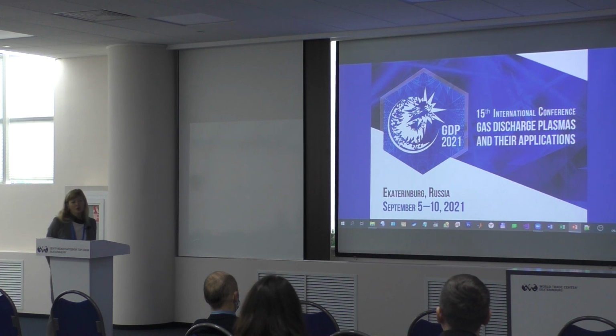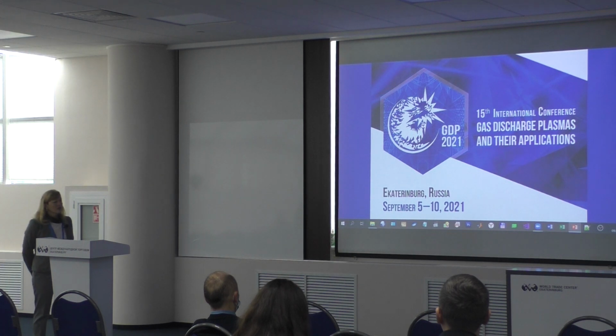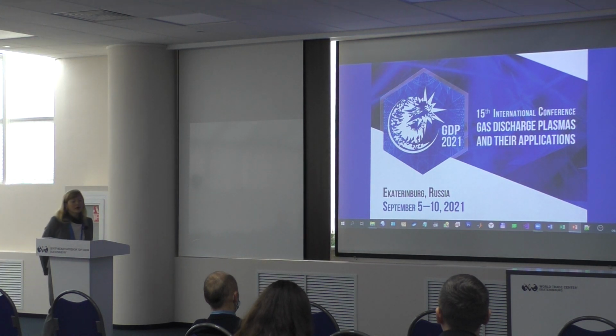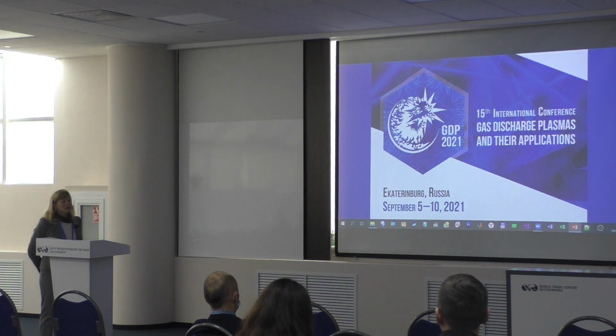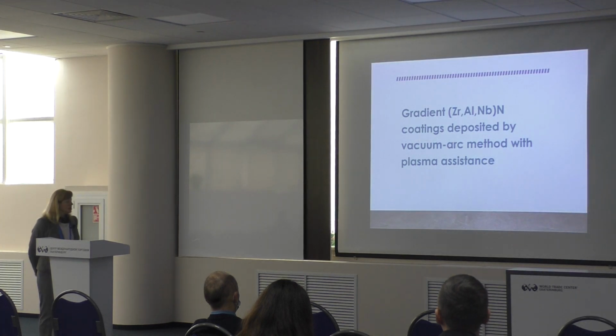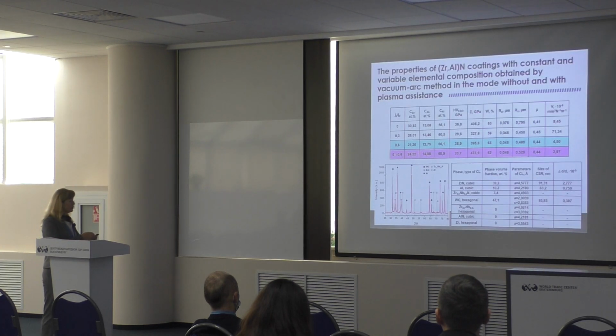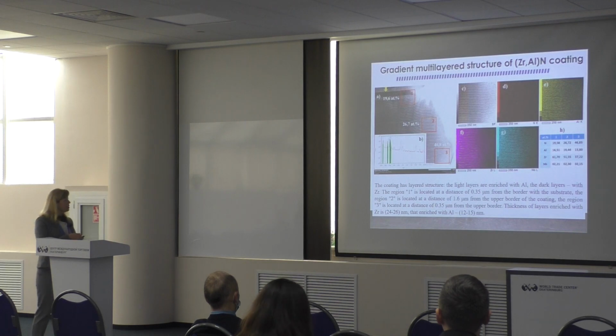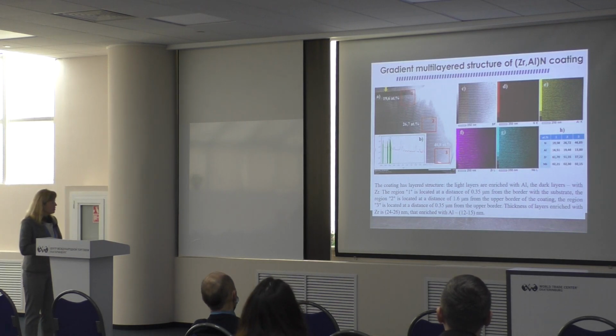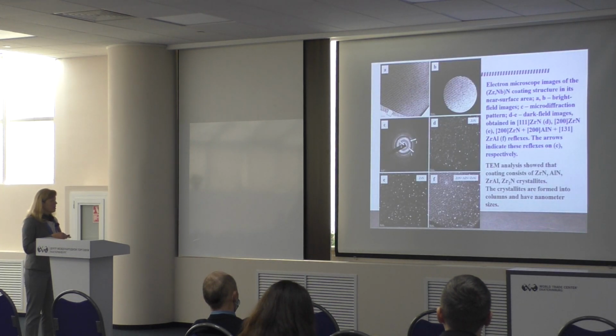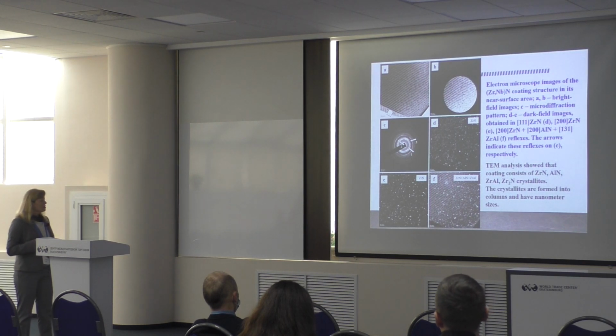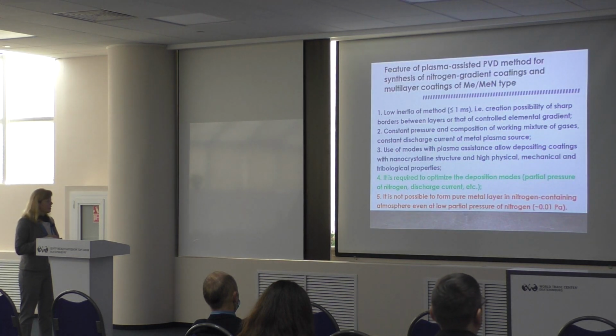Coatings of zirconium, niobium, aluminium nitride have high hardness, high elastic recovery, and very low wear rate, and we can use them as wear resistant coatings. You can see the concentration gradient and also the multi-layered structure. The crystallites are formed into columns also, and have nanometer sizes.